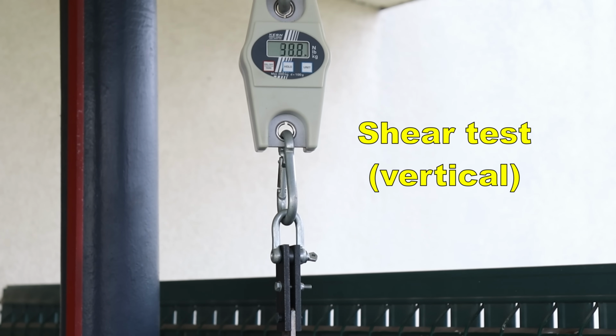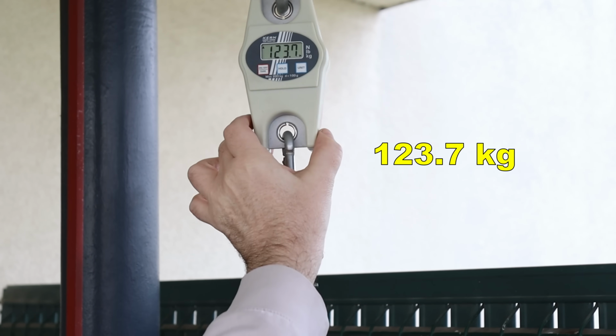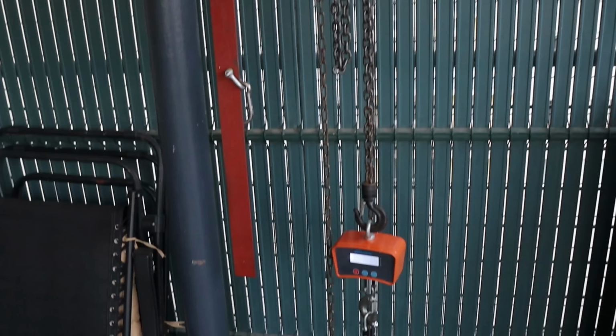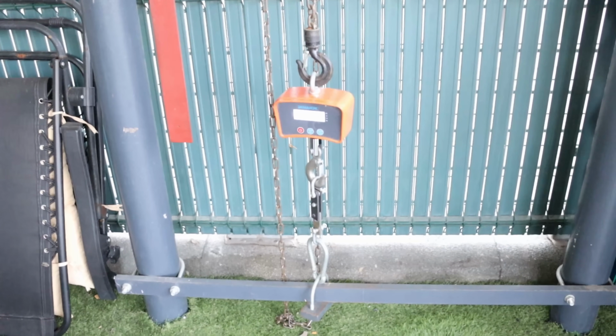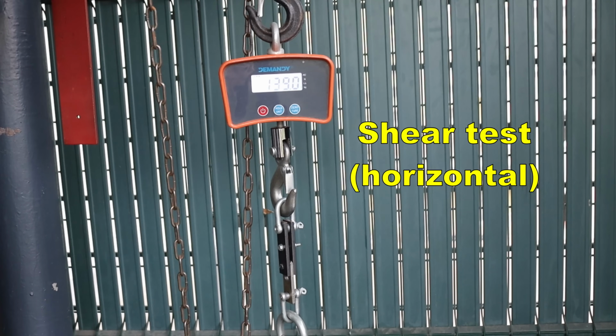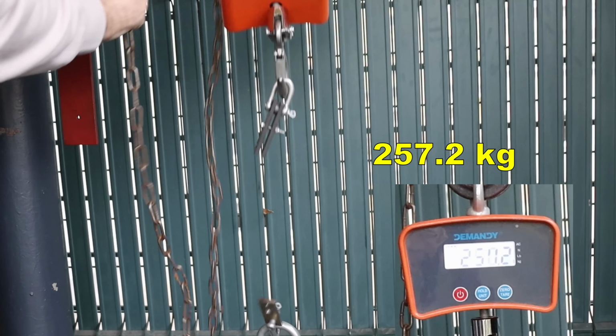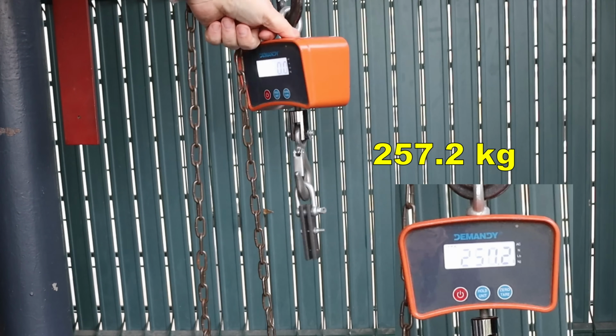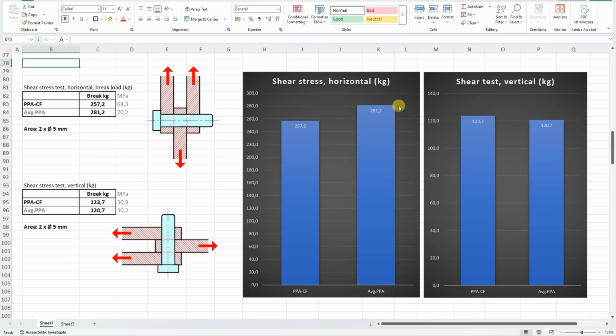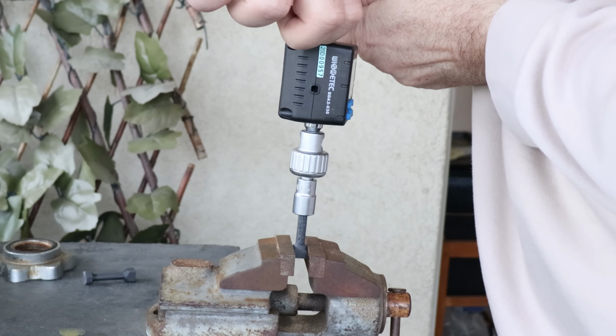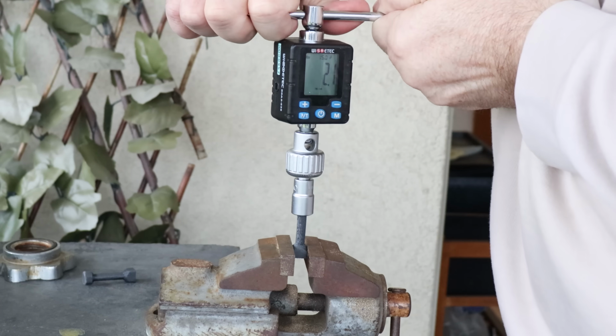Shear test, and I'm starting with the vertically printed ones. And for the horizontal shear test, I'm switching to stronger equipment because I know that 200 kilograms is not enough. Printed in horizontal position, with all PPA filaments I had to switch to that stronger equipment because 200 kilograms are not enough. And yes, in this case the average PPA is stronger, but the difference is negligible, I think. And similar with the vertically printed test objects, and in both cases these are extremely strong compared to any other filament type.